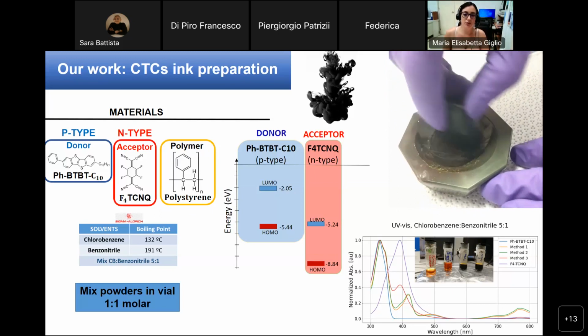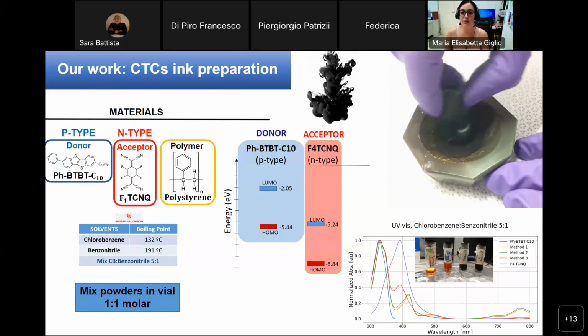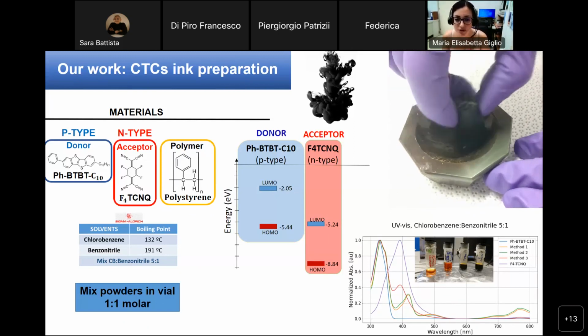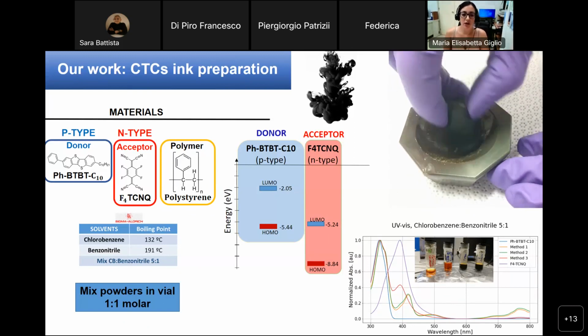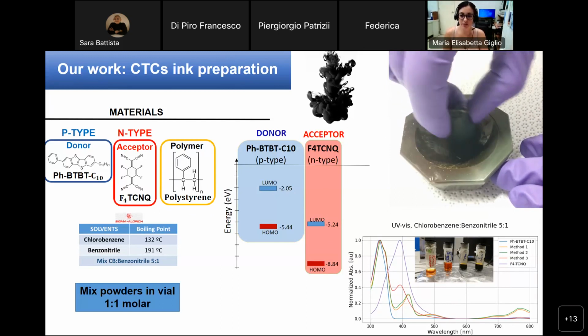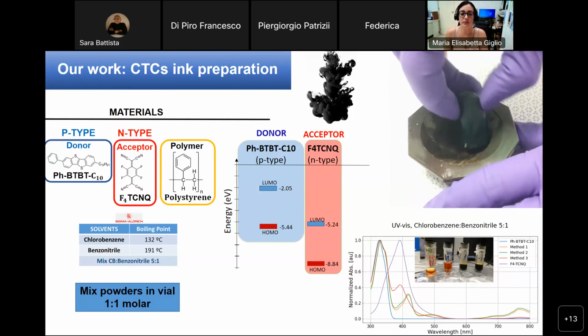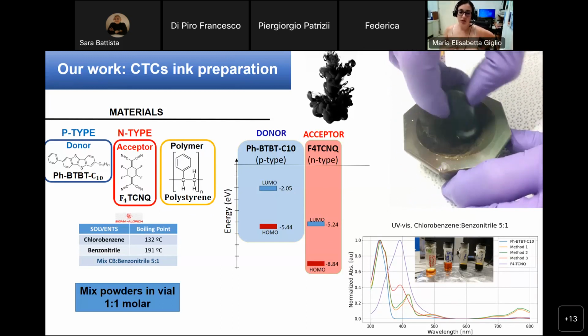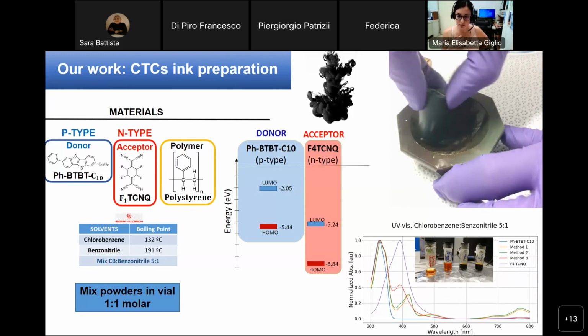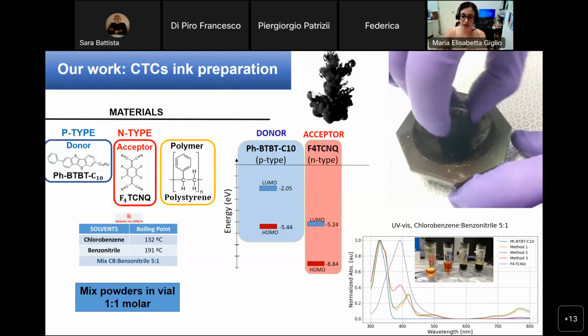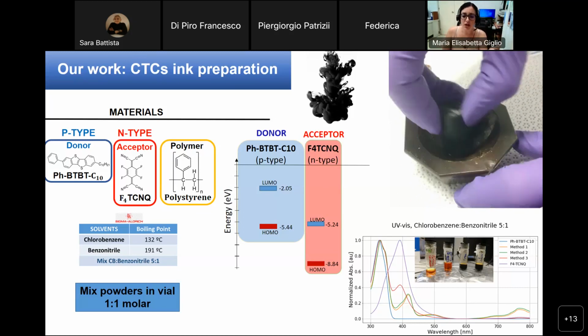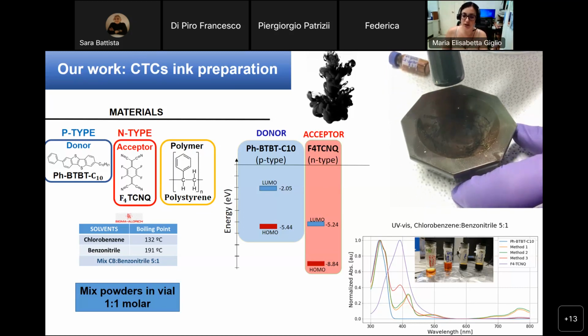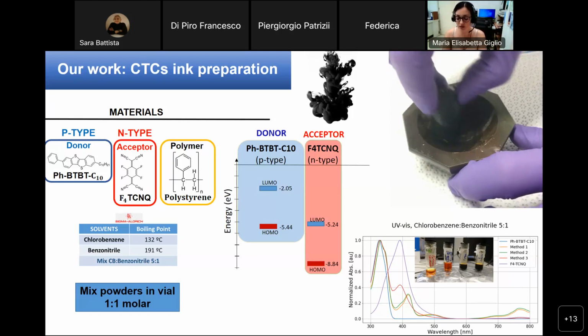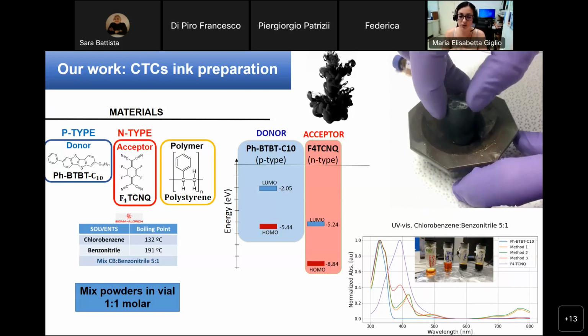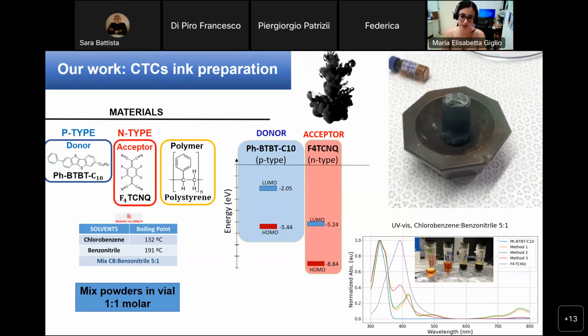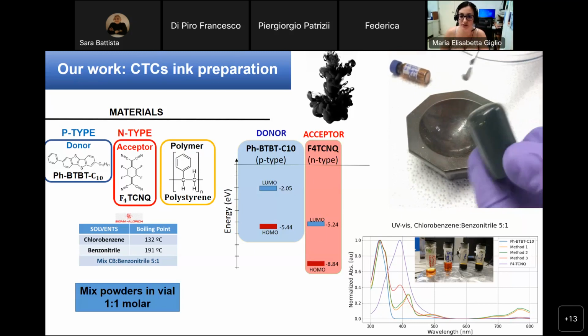So basically what we do here is, well, we try different methods. One is the one that you see in the video, which is mechanochemistry. So we mix the two materials as powders and then we dissolve them. And we also perform ultraviolet-visible spectroscopy in order to see changes in the peaks. And then we can also see a change in the color of the solution when the donor and the acceptor are interacting and forming a charge transfer, because basically the solution turns black. So it's clearly visible and it's very nice to see.